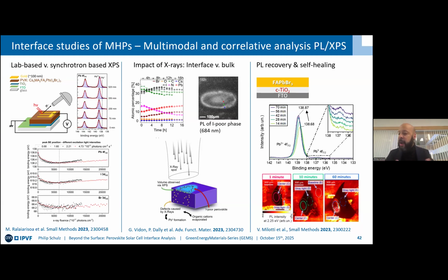Now we could ask ourselves, so how long will it actually go? Well, we could actually see that when you make your surface devoid of any formamidinium, bromine is still there, by sputtering, for instance, you hold X-rays on it and you can see a re-emergence of the nitrogen peak as formamidinium is again reconstituting the surface.